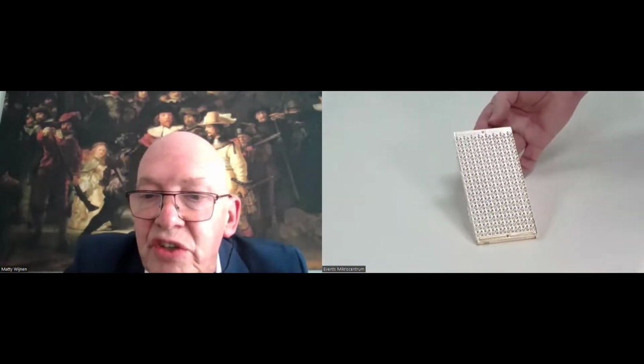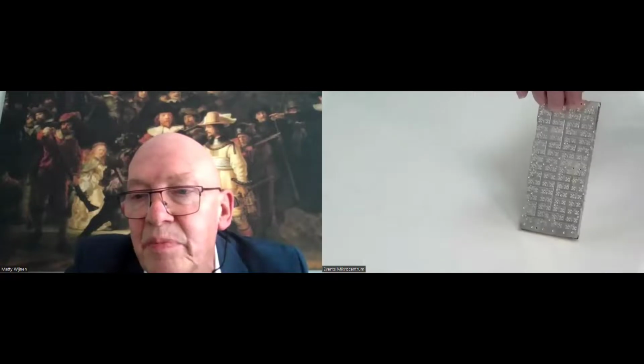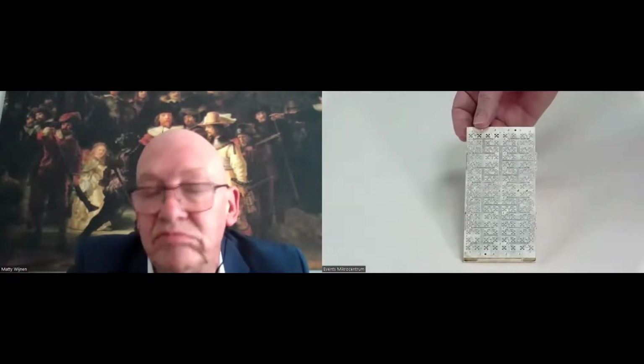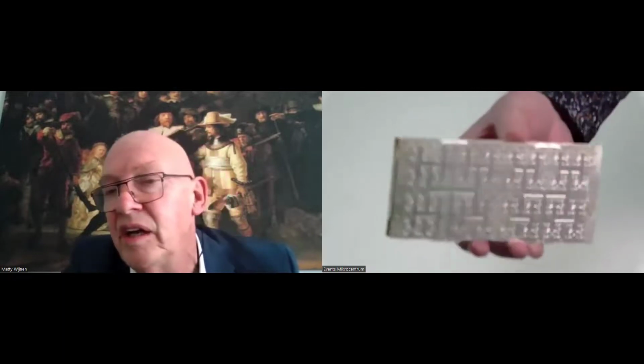These are parts which are used in the antenna industry for airplanes. And these parts, with very small holes, all have to be coated with silver. But we put on a nickel layer because it's an aluminium part. If you put it directly on the part, it's technically possible, but you would have a lot of corrosion. With a chemical nickel underlayer, you have a nicely coated, completely coated part.